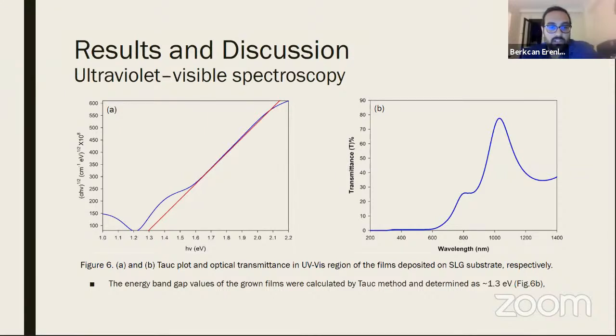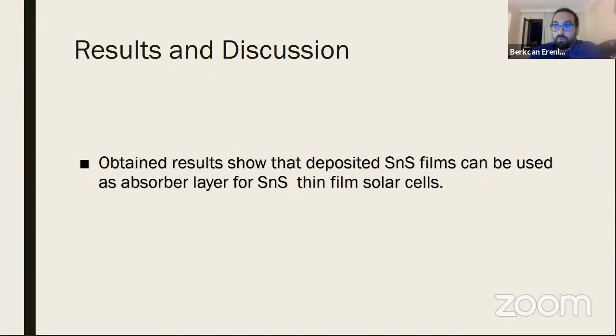UV-visible section. Figure 6A and B show the optical transmittance spectra and energy band gaps of the tin sulfide thin films. The energy band gap of the tin sulfide thin films was calculated by the Tauc method and is 1.3 eV. The obtained results show that the deposited tin sulfide thin films can be used as an absorber layer for tin sulfide thin film solar cells.